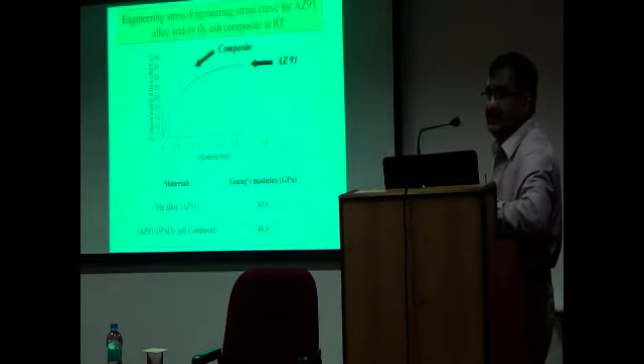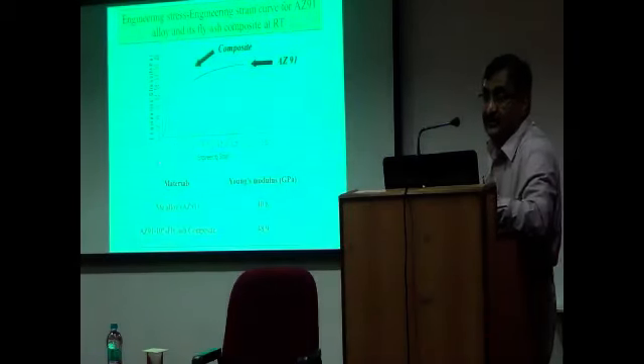You can see how the stiffness changes. As simple as fly ash can change the stiffness, the elastic modulus of the material significantly, by using fly ash, which is almost zero cost. It doesn't cost you, but it's available. So you bring this to the magnesium, and it changes the properties significantly.